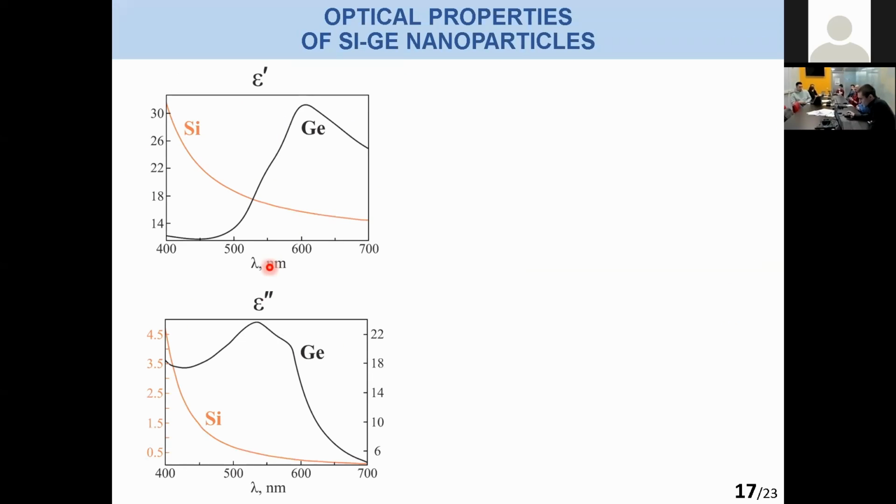So, as I mentioned before, the imaginary part of the dielectric constant of silicon-germanium differs significantly at the green laser wavelength that is used in the Raman setup, and the real parts of the dielectric constant at this wavelength are pretty much the same. According to this, two values were calculated.